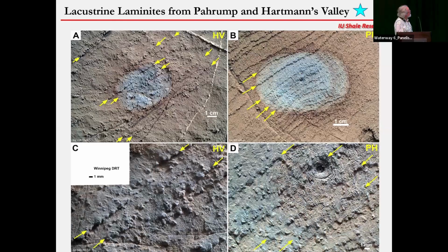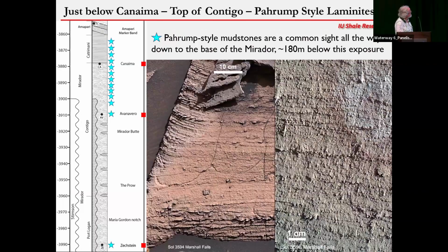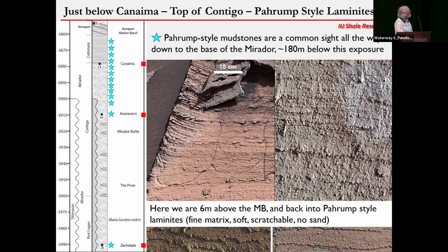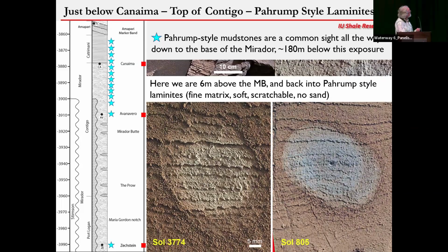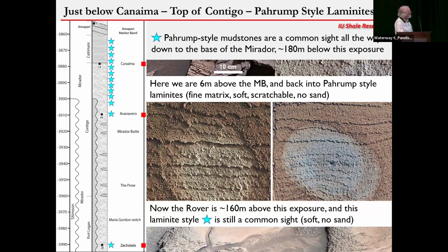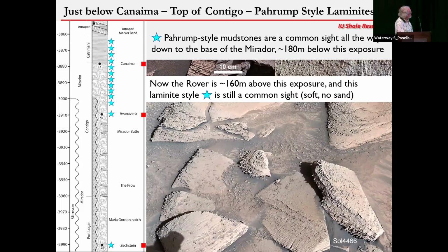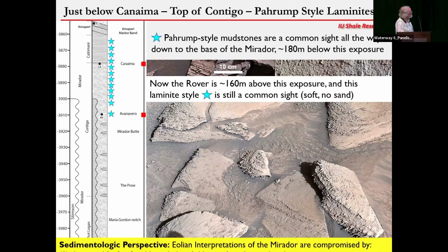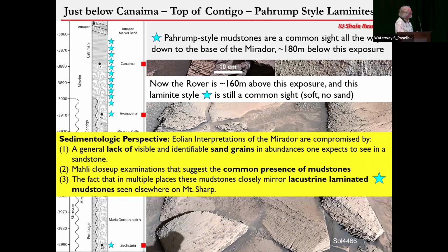So talking about the first point, the lacustrine laminites, these are laminites that we saw at Pahrump and at Hartmann's Valley, and you see these lamina that are those hardened lamina that have the little crystallites in it, which are basically evaporite pseudomorphs. We see very similar kind of stuff here at roughly in this area here. And then you see it also above the marker band, up here. You see again these nice lamina. And here we have this lacustrine appearing lamina 160 meters above the marker band exposure. And it still looks very mudstone-like and like the other ones.